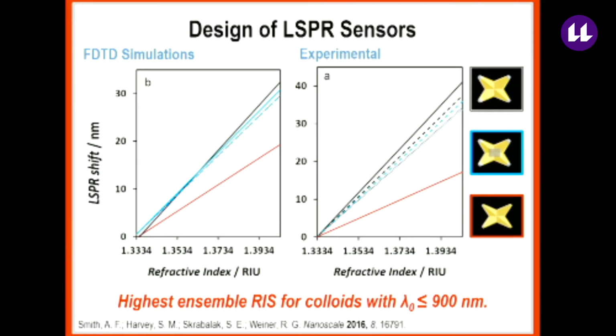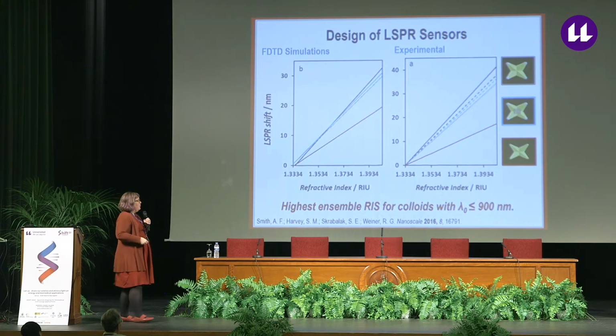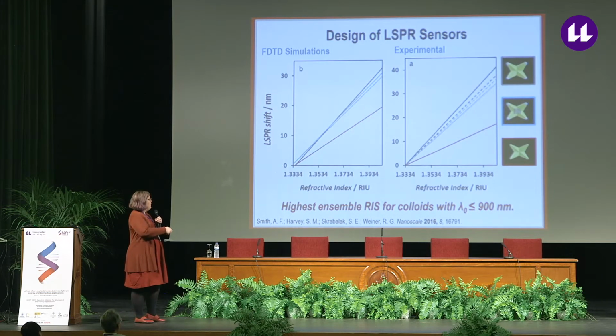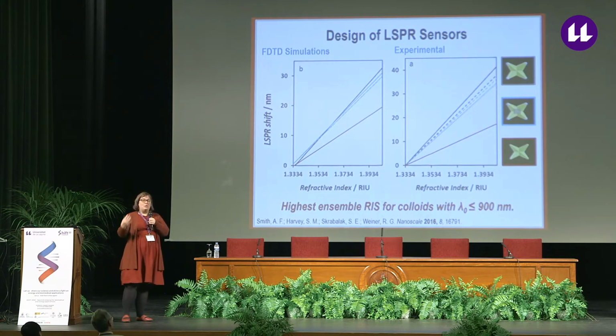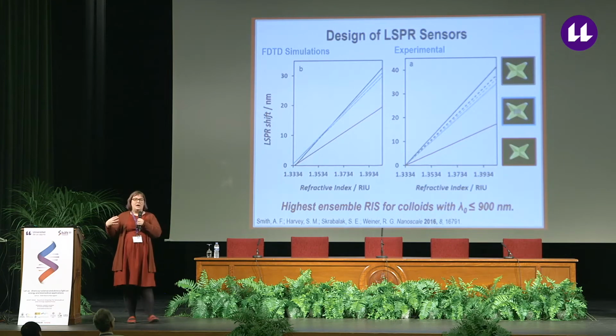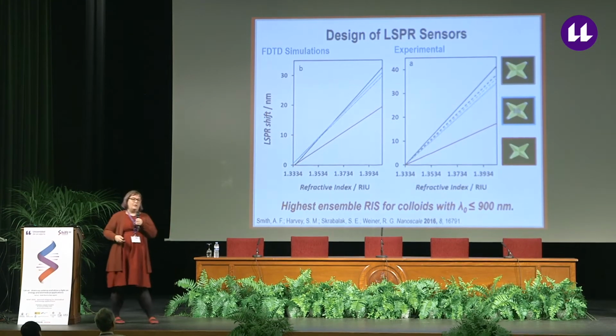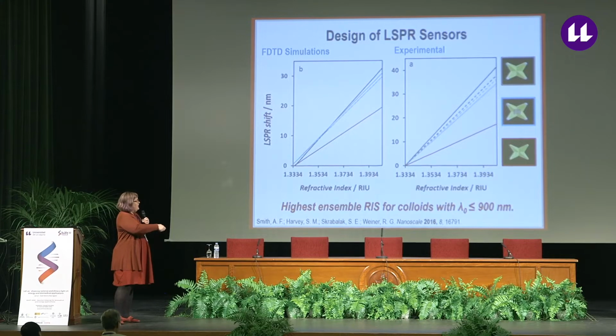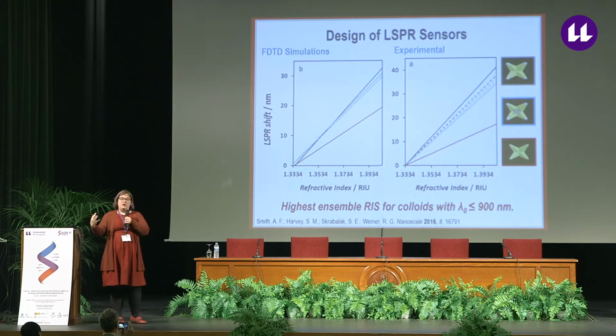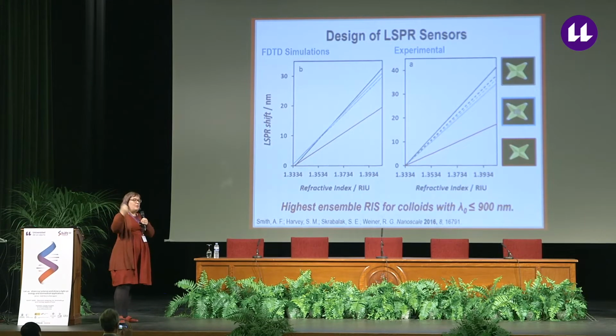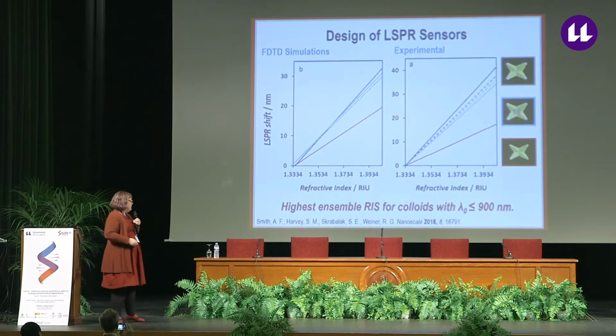So then we went into the lab and took a number of our different nanocrystals. We can make all gold octopodal nanocrystals, as well as ones that have the palladium core. And what we found was pretty good agreement between our simulations and experiment, even though we had grossly simplified our models in the simulations. I think the key takeaway is that the all gold structures are the least sensitive to changes in local environment, whereas having palladium at the tip gives a significant boost in sensitivity.